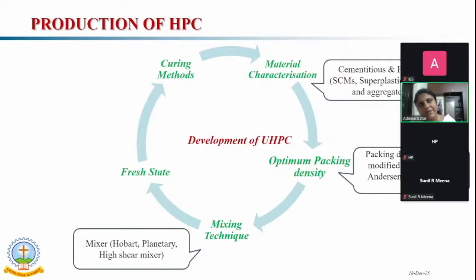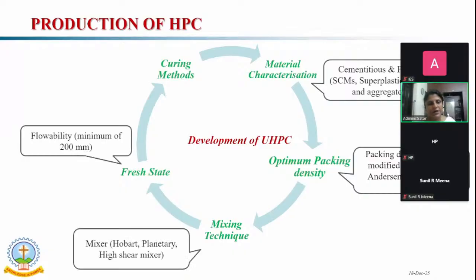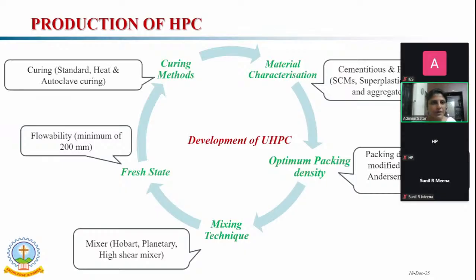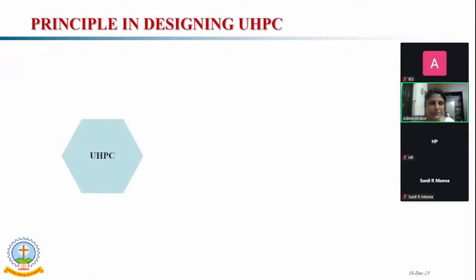That will be discussed later. The mixers we have in the laboratory, we have used the Hobart and planetary mixer, and also we have done that experiment. Then we have developed the UHPC with 150 MPa in the high shear mixer, that is an RMC. Flowability we have considered, as I said earlier, minimum 200 mm. There are three types of curing methods: standard, heat, and autoclave curing. But in this case, we have considered only standard curing and the heat curing method.